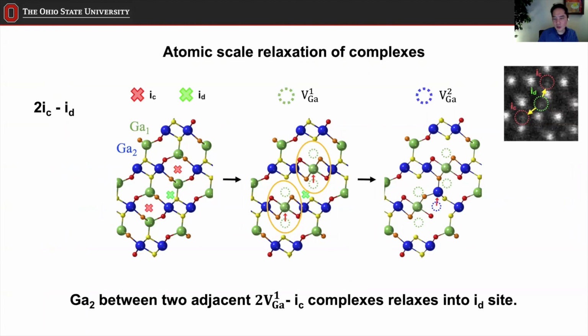Unfortunately, we cannot get the charge information directly. One piece of information that is missing, and this can be misleading, is that there is no information about the oxygen directly. We are showing the oxygen positions, but in this particular type of data it is difficult to get the oxygen intensity, so all the oxygen positions are guessed. We speculated those positions. They're supposed to be there, so we draw them there. But it's possible that some of the oxygen positions are empty, or they may be displaced, and that could certainly affect the charge of the entire area. So the short answer to your question is we don't have any charge information, and therefore I cannot say anything about how the charge is being compensated.